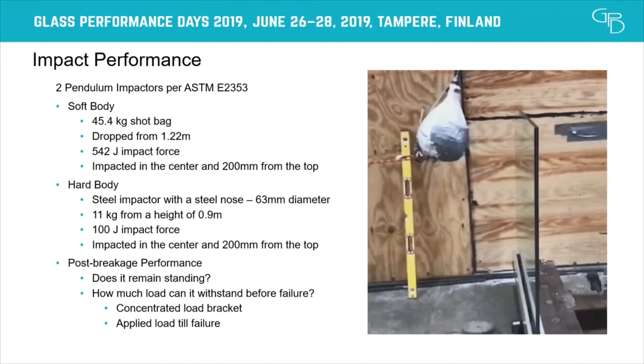So now we move on to the impact performance. According to E2353, there are two pendulum impactors. One is the soft body. This is the 45 kg shot bag that's dropped from a height of 1.22 meters. For this one, according to the standard, it has to be impacted close to the top and in the center of the glass, so maximum impact there. There's a hard body impactor with a small round metal ball at the tip that impacts the glass. This one was 11 kgs and it was dropped from a height of 0.9 meters, so it delivered 100 joules of impact energy.